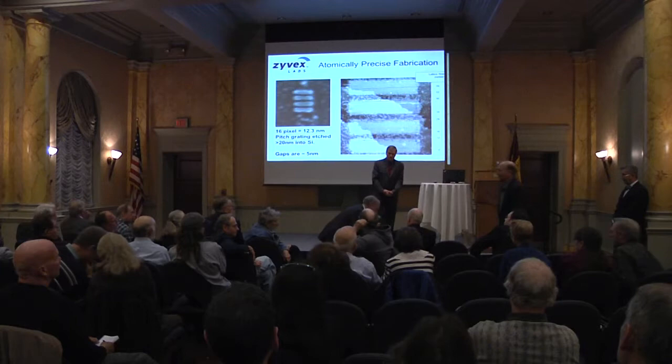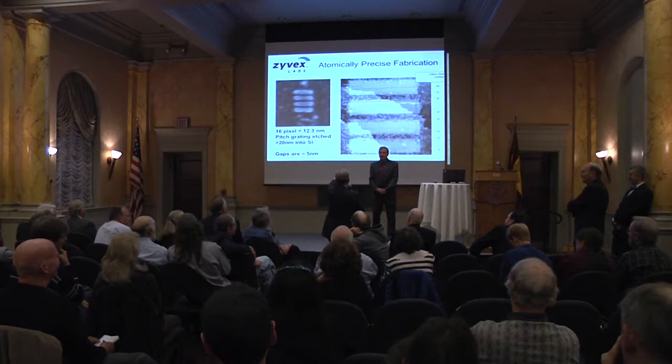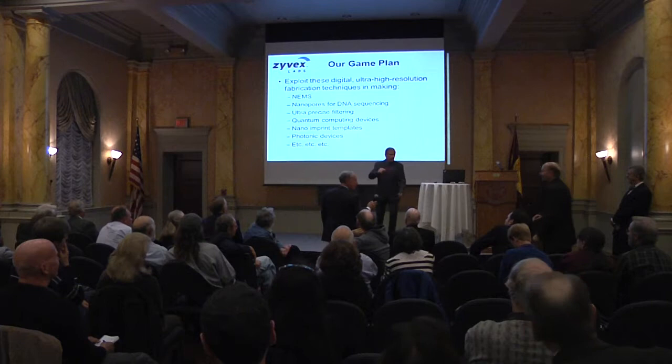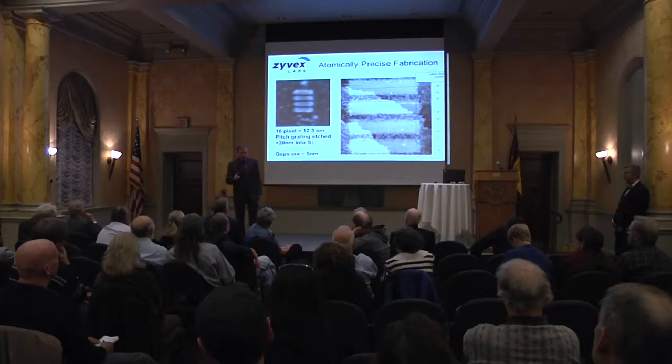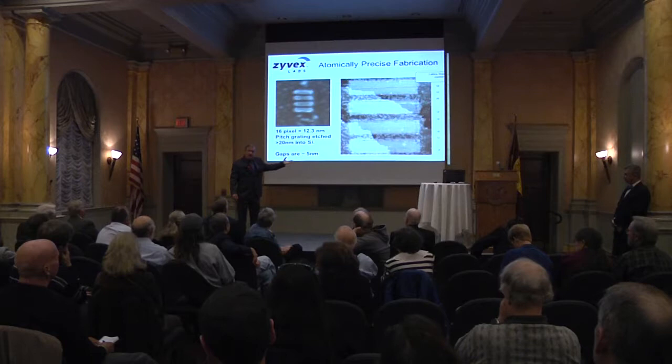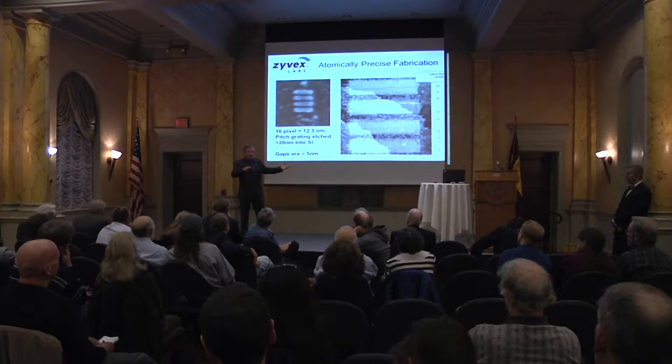I'm Bob. Yeah, I'm a member. Could you talk about the time element of this, of how long it takes to put down an atom, and how long these patterns that you're showing here? Well, it's a great question about patterns moving. We spent a lot of time looking at the mobility of hydrogen on silicon surfaces, and at room temperature, they just don't go anywhere. But to do this pattern growth of silicon that we're trying to do, we have to operate at about 250 to 300 degrees C. At 300, the hydrogen starts moving around, okay? But below that, if there's any motion, it's very, very subtle.